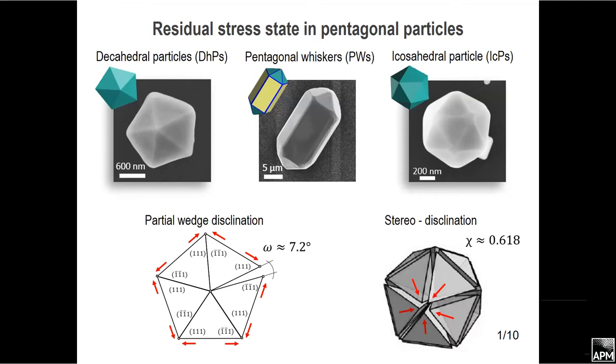These particles are characterized by a high level of residual stress, which is attributed to these particles of pentagonal symmetry, which is actually restricted by the classical rules of crystallography, the five-fold symmetry axis. And this fact induces in these particles some residual stress, which is illustrated on this sketch. Like if you should fit this gap, and it induces some strain.